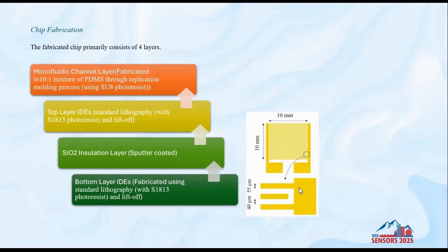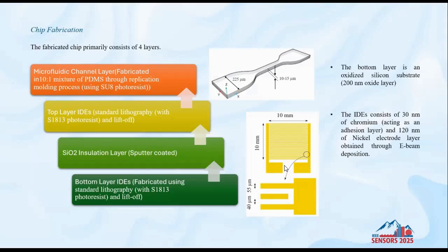As can be seen in the bottom right corner of the screen, the interdigitated electrode dimensions are shown here with a 40 micron inter-electrode gap and a 55 micron electrode width. The whole electrode area is 10 by 10 millimeter square. So the microfluidic channel can contain a total of around 100 nanoliters of fluid.